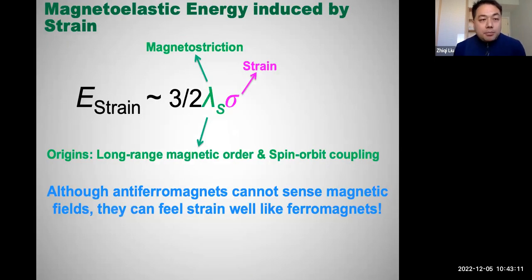Now, if you look at the principle for this kind of piezoelectric strain controlled memory antiferromagnetic spintronic devices, the key element is the magnetostriction energy. That needs a strain and also needs a magnetostriction. We all think that the magnetostriction exists for ferromagnets, but indeed it also exists for antiferromagnets. It comes from long-range magnetic ordering as well as spin orbital coupling. So we can now say, although antiferromagnets cannot sense magnetic fields, they can feel strain as well as ferromagnets.